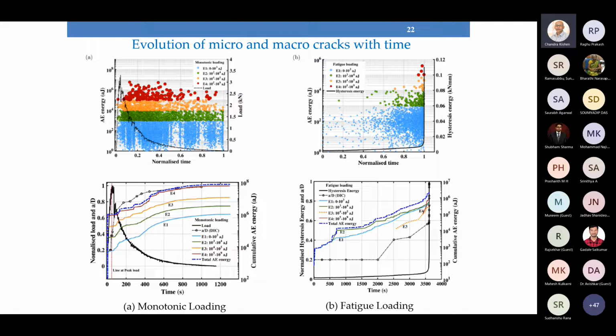So in the case of a monotonic static test, right from the beginning, we see all energy levels present in the events, and there is a simultaneous interaction, especially during the softening region. We see the growth of micro cracks to be very large, and at final failure, this reduces. Whereas in the case of the fatigue test, almost up to 75% of the life, not many micro cracks are formed, and we don't see these red dots during the initial life. It's because only small cracks are formed. They are dispersed across the depth of the specimen, and only during final fracture do we see these red dots, indicating that all these minor cracks coalesce to form a major crack, and sudden crack propagation takes place.